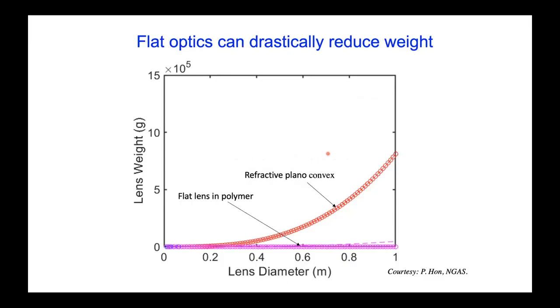This is a chart put together by Philip Hon at Northrop Grumman last year or so, where he plotted the weight of optics versus its aperture size. Obviously, as you scale the aperture size, the diameter, the weight increases, of course, in a nonlinear fashion for conventional lenses, because you need a bulk material in order to refract the light. However, once you go to flat optics, the increase can be dramatically reduced. This becomes even more significant at very large areas. I'll mention briefly why that's important, particularly related to astronomy and space applications.